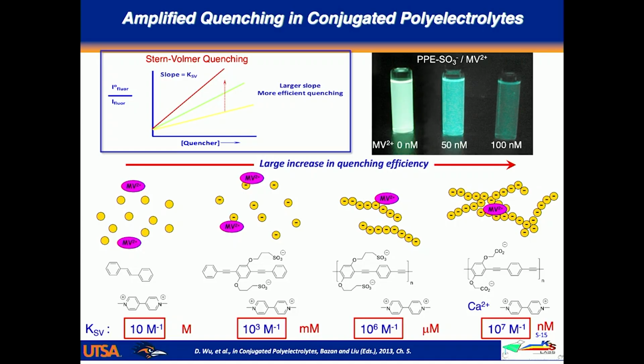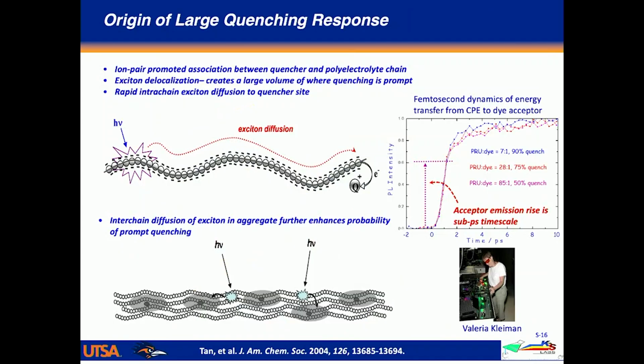So now, one of the things that my group has been interested in over the years is what is the mechanism of this effect? And I'm not going to give you a long story about that, but I'll just tell you that it really has two components. The main component is this static quenching, meaning that the opposite charges bring together the quenchers and the polyelectrolytes. That enhances the probability of the exciton being in close proximity to the electron acceptor or the energy acceptor. But then there's also an effect that has to do with diffusion of the excitons along the polymer backbone. And this is actually what, if you read the original Swager paper, he really sort of emphasizes this effect. But it turns out, in my estimation, the exciton diffusion is not as major a role as really just the static quenching part, that is, the two species coming together and being in relatively close proximity.